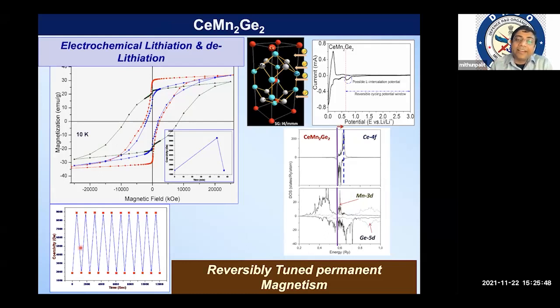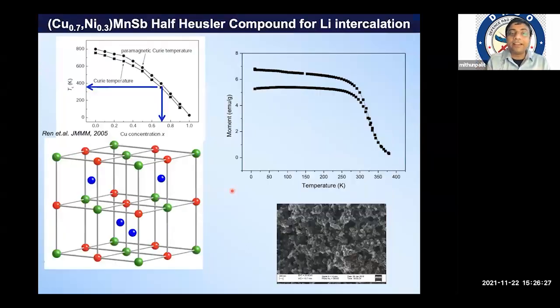So a medium coercivity material can be converted into a hard magnet, and then the hard magnet is again converted to a medium coercivity material. Such smartness you can use for any kind of switching or any kind of lifting application. And you see that it is not valid for only one cycle. We have cycled it many times, and you find the coercivity systematically changing from 2000 to 10,000 and back. Otherwise CeMn2Ge2 cannot be classified under smart material. However, we could make it a smart material with this kind of lithium ion battery concept.